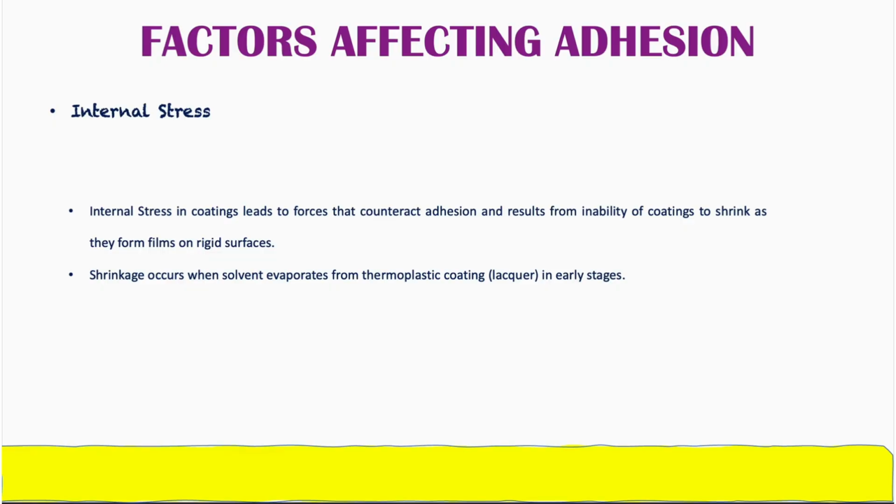For example, in UV curing of acrylated resins, when we use the free radical polymerization process, it occurs in a fraction of a second at ambient temperature. But the high rate of polymerization, together with the relatively large shrinkage that accompanies the polymerization of double bonds, contributes to the generally observed poor adhesion of UV cured acrylated resins to smooth metal surfaces. We'll understand this particular aspect in another way.